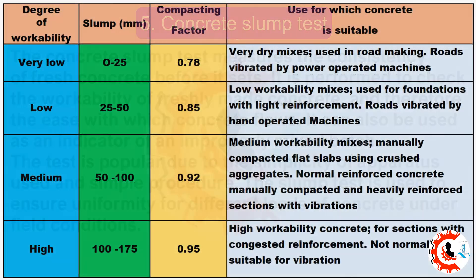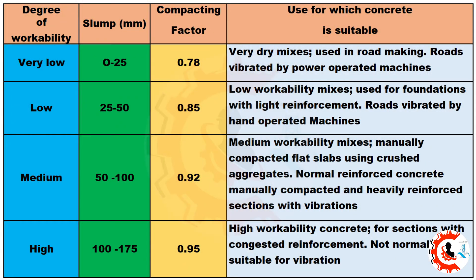Degree of workability. One: very low slump, 0–25 mm. Compacting factor = 0.78. Suitable for very dry mixes used in road making, with roads vibrated by power-operated machines.